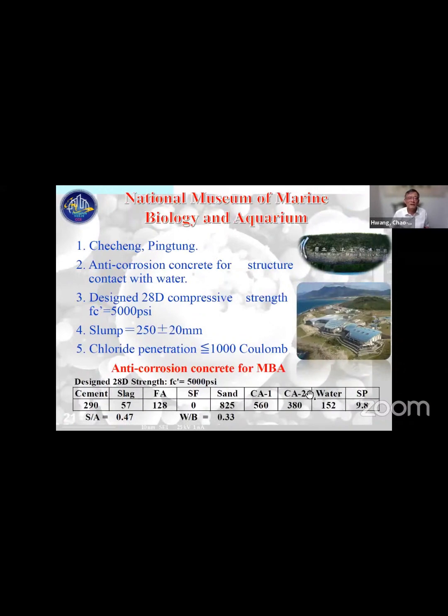And the Museum of Aquarium, marine biology aquarium, okay. So that uses 290 kilograms of cement. Normally this kind of cement, they need more than 300, and for 5,000 PSI concrete, need 500 kilograms of cement. So you can see that this concrete only uses less than 50% of cement. Not only do we use it to replace cement, but we fill the void of sand, so they can contribute major strength.